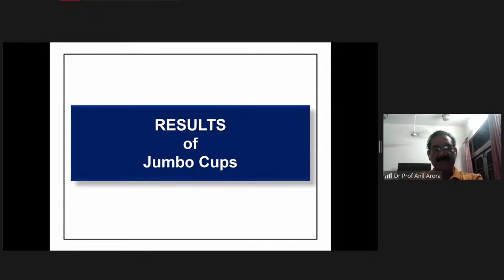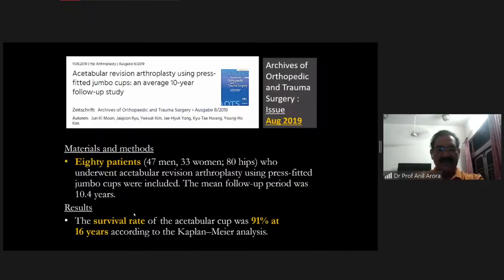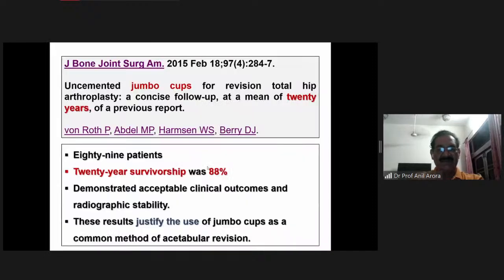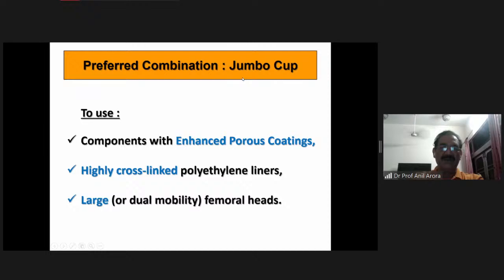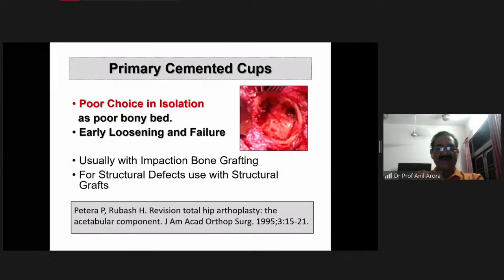How have been the results? In 80 patients, the survival rate was 91% at 16 years with the jumbo cup. Another study, 20 years results, survivorship was 88%. So jumbo cups, if done with proper indications, have a great survival rate. That's the recommendation for the jumbo cup combination. Preferably use enhanced porous coating if available. Use a highly cross-linked polyliner and a large or a dual mobility femoral head. Cemented cups in the revision scenario have not fared well. They are a poor choice in isolation as there is a poor bony bed.